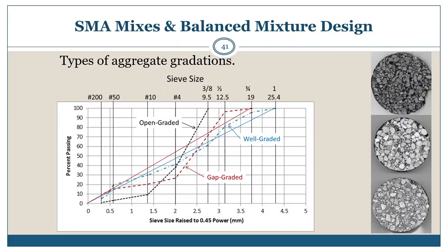Comparing gap-graded to other mixtures, the dense-graded or well-graded aggregate gradation, shown in the dashed blue line, has gradations close to the FHWA maximum density curve. In other words, it typically has lower voids in the mineral aggregate, and then requires lower asphalt content. It refers to a sample that is approximately of equal amounts of various sizes of aggregates. By having a dense gradation, most of the air voids between the particles are filled with aggregate particles. As shown in the figure, a dense gradation will result in an even curve on the gradation graph, resulting in lower voids in the mineral aggregate and requiring lower asphalt contents.